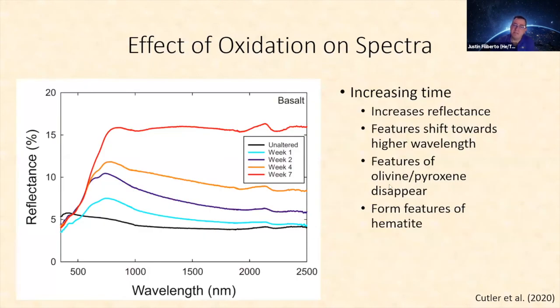We did spectroscopy. These are not offset because these tell actually really nice stories. So we've got a very flat, unaltered basalt here, 1 week, 2 weeks, 4 weeks, and 7 weeks. We are getting a brighter and brighter spectrum. We are losing the peaks or the features dedicated to basalt, and we're getting a spectra that looks very much like hematite. So with increasing time, we are going from reflectance at 5% or emissivity of 0.95 to reflectance of 15 or emissivity of 0.85.